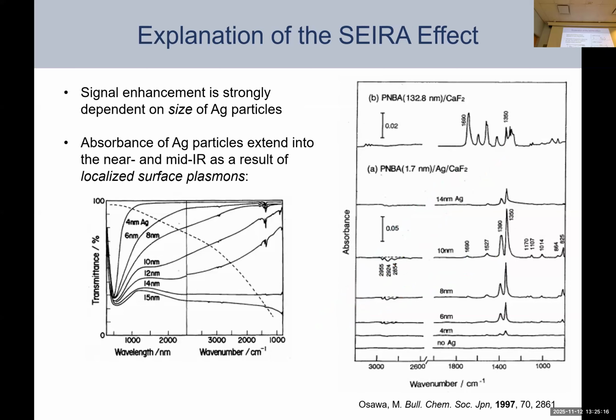So here's a nice plot showing the percent transmittance from different silver nanoparticles. You can see the smallest nanoparticles, 4 nanometer diameter, have this really sharp feature, and then essentially flat as we go out to larger wavelengths or lower wave numbers. Okay, sorry, this is going from the UV, UV visible, into the IR here. And then as we increase the size, you'll see that there's this really large, broad feature here. Okay, and so this is coming into play as a really important aspect for ATR-SEIRAS.